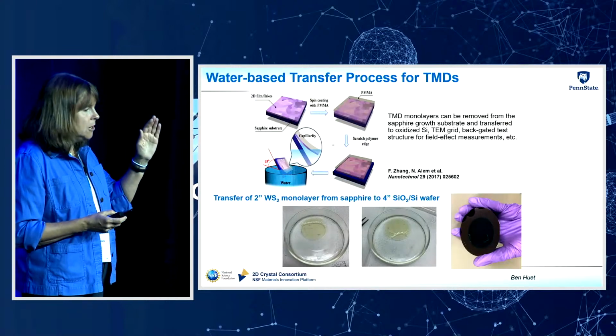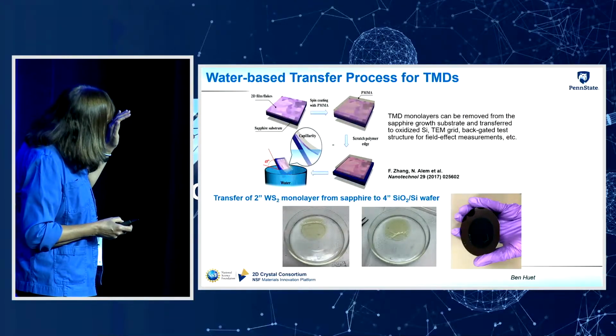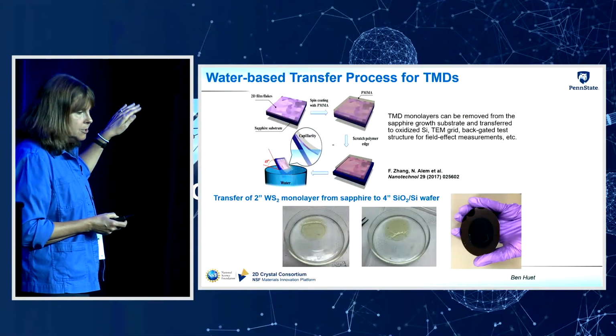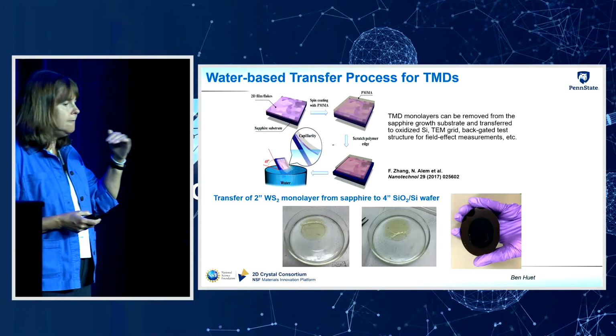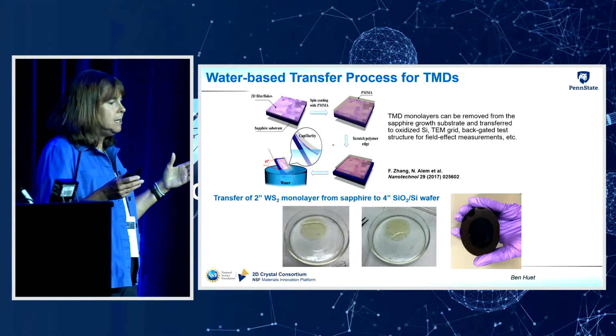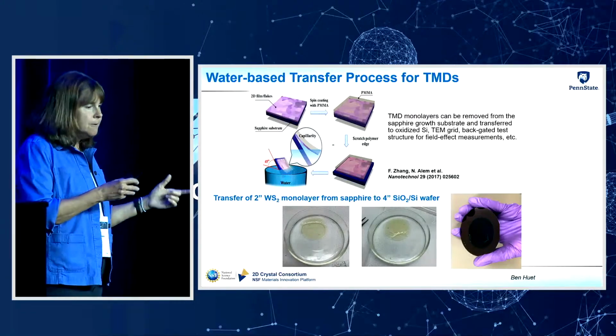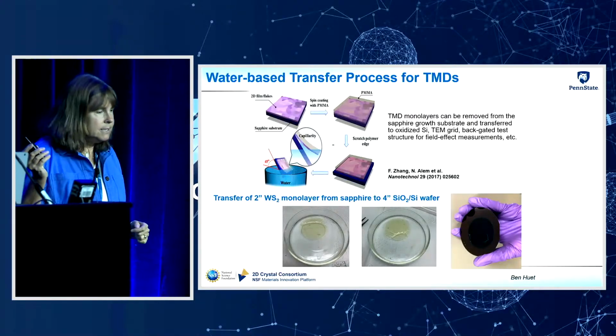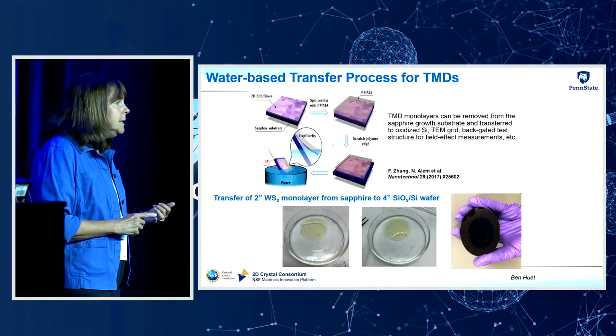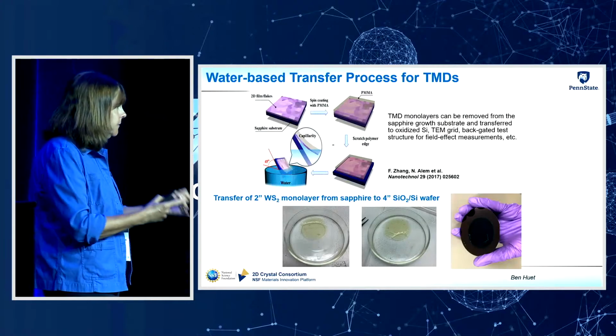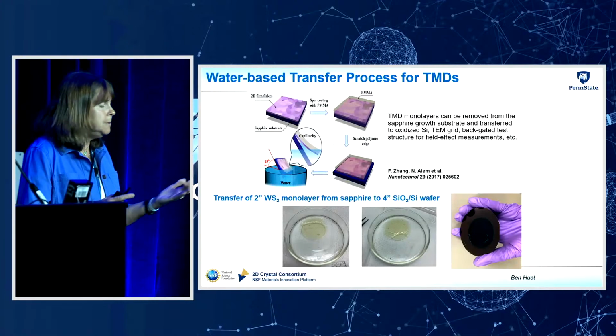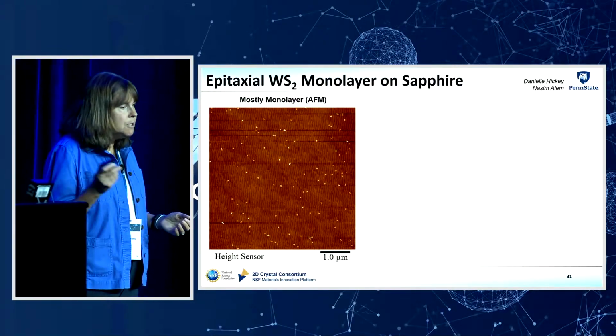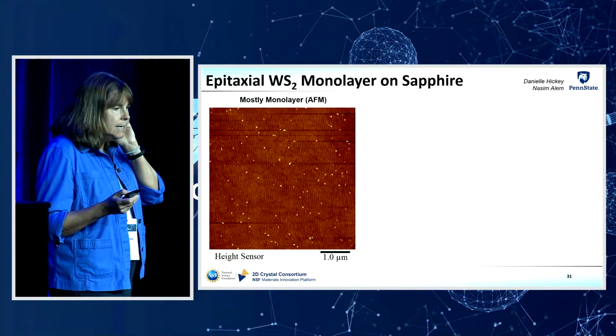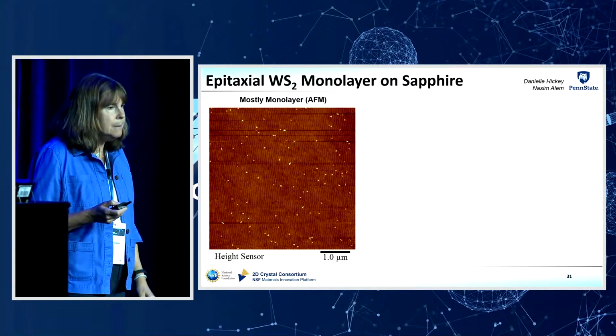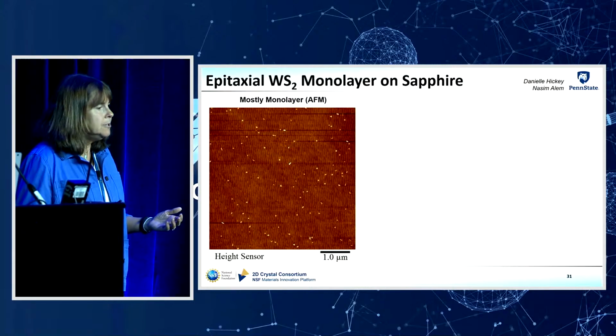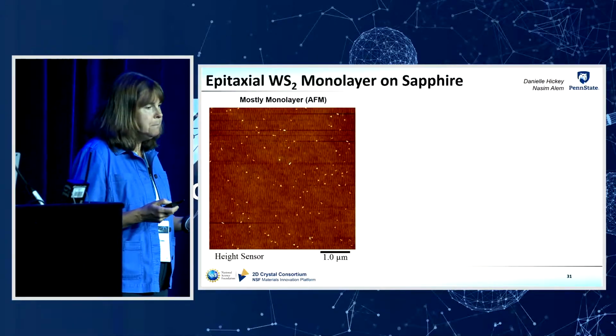So we can lift off our tungsten disulfide, and the bottom is just showing a couple of photos where we have transferred a 2-inch tungsten disulfide monolayer from sapphire onto an oxidized silicon wafer, or we can transfer it onto a process device structure or onto a TEM grid. So we worked with our collaborators, Danielle Hickey and Nasim Alem, to do TEM characterization of these tungsten disulfide monolayers.